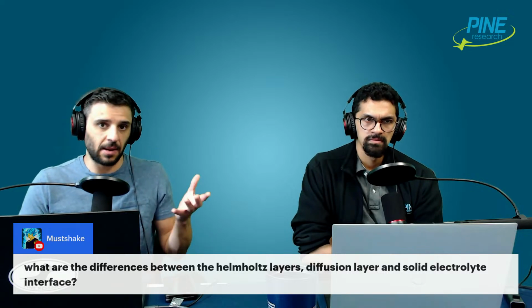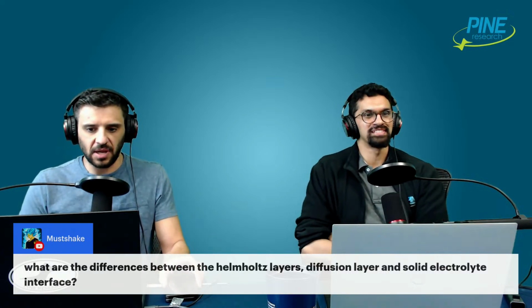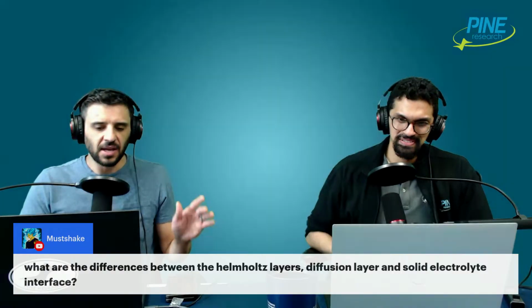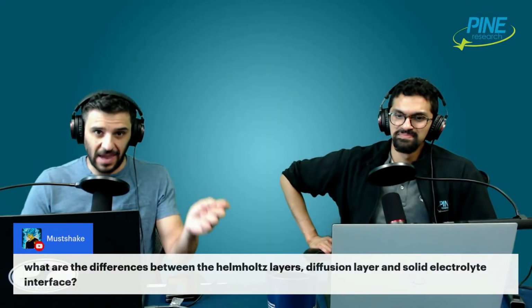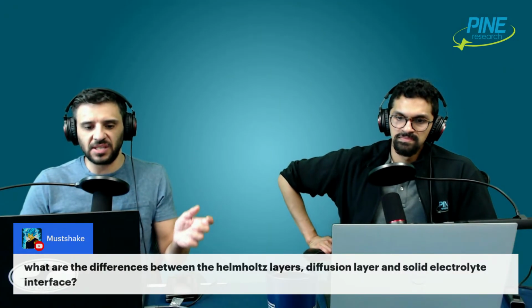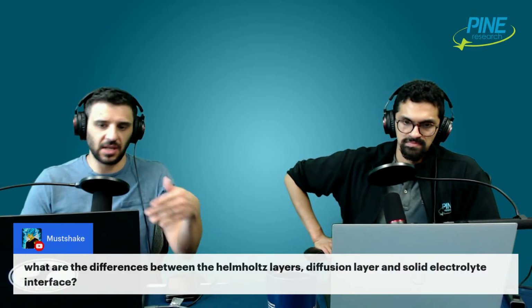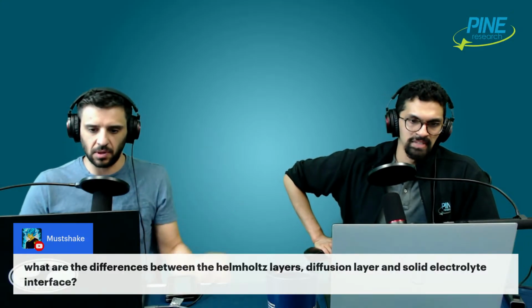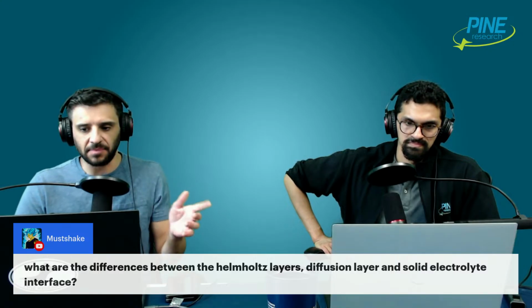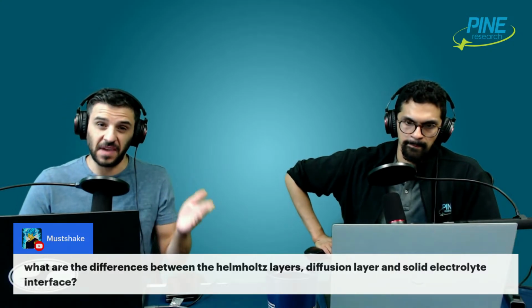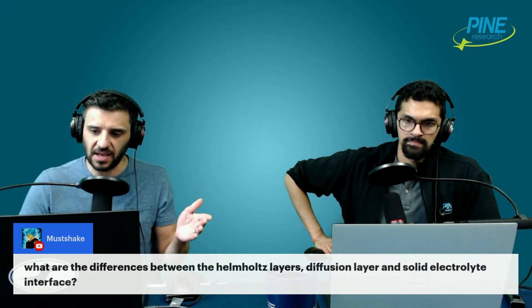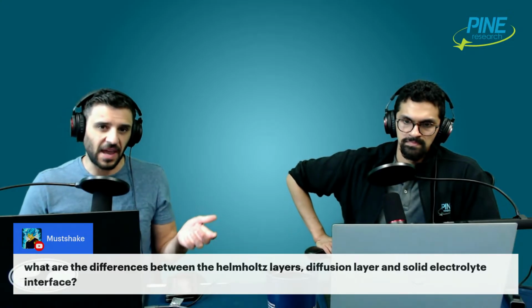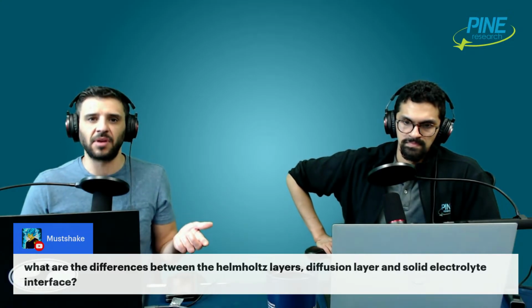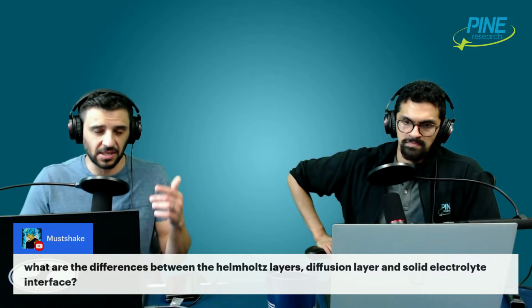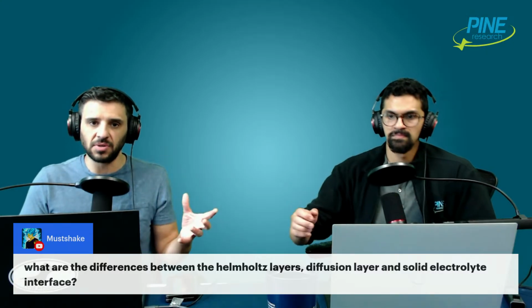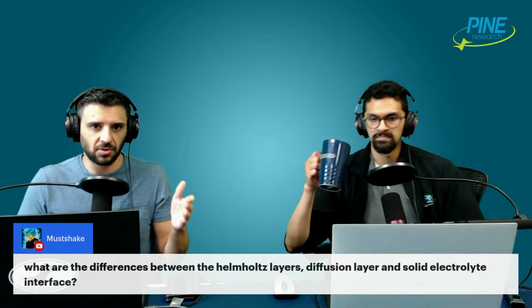The other option is at a battery. Oh yeah, that's right, the other option. And this is a tricky thing: whether we're saying interface or interphase. Usually when we see interface, it's just referring to the place where the liquid touches the metal. Sometimes people will say interphase. The solid electrolyte interphase is a separate phenomenon that occurs on a battery electrode, whereby part of the electrolyte is dissolved and decomposed to form a film on the electrode surface.